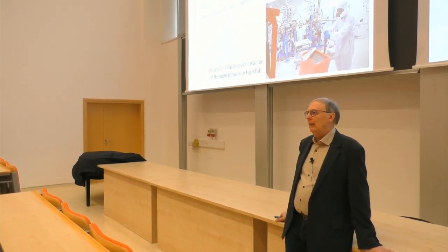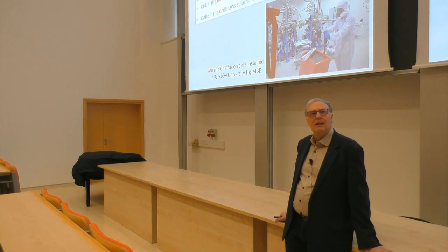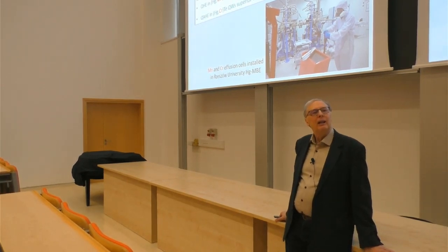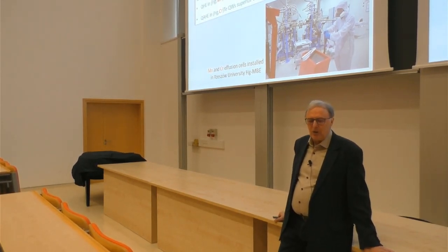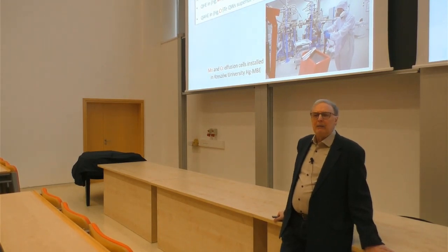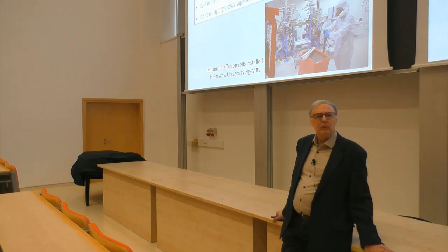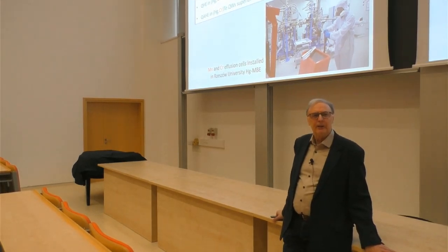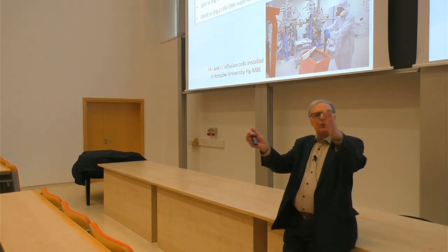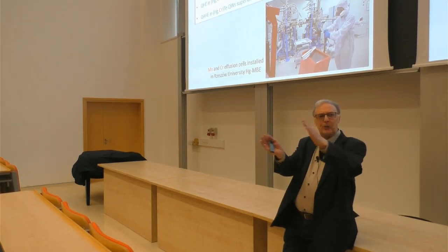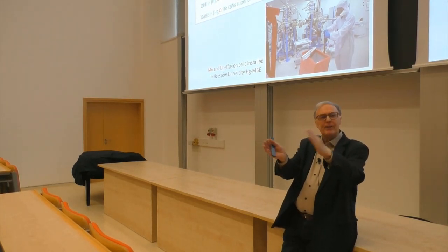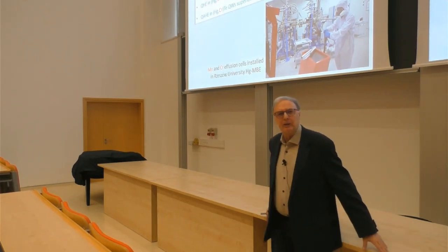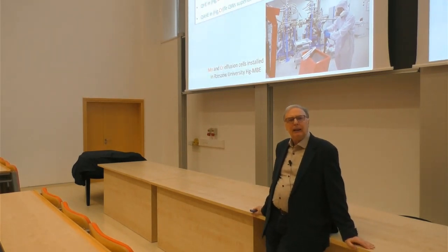And is homogeneity of the sample critical in that case? Homogeneity, well, of course, if you have precipitation of chromium, it will probably kill the quantum Hall effect. We have to have a more or less homogeneous distribution. Zinc telluride with chromium was already used to produce splitting of bands in bismuth compounds. So we hope that it will be possible to have mercury chromium telluride. Thank you.